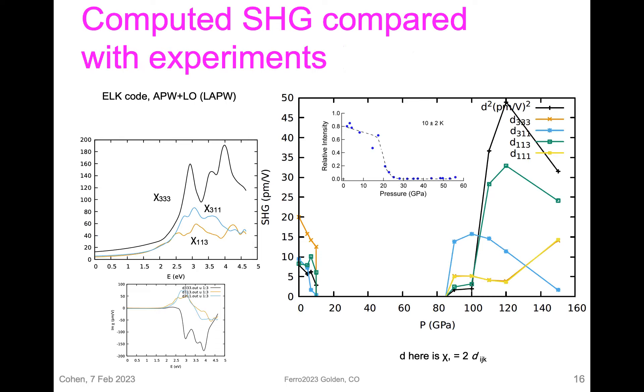The last thing I want to say is I also wanted to see if we could compute what the second harmonic signal should look like. I had some hopes that it would be weak at a megabar, which was why they didn't see it in experiment, but that was not the case. This shows the computed second harmonic signal, and it does seem like it should come back, though it is somewhat orientation dependent. If you have really a powder, you should see something above 80 GPa.